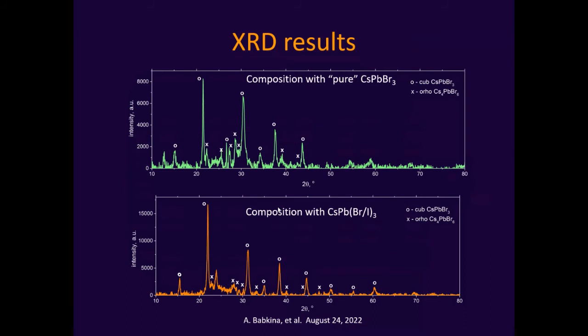What about XRD? Of course, when we're talking about nanocrystals or other crystals inside of the glass matrix, we of course need XRD. The problem with nanocrystals is that when we are working with a small number of nanocrystals inside of the glass matrix, we see luminescence and we see the absorption spectrum, because the intensity of the exciton absorption is really very high. That's why we need a low concentration of crystals inside of the glass to measure the absorption spectrum.